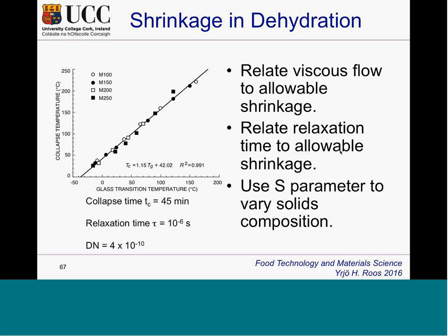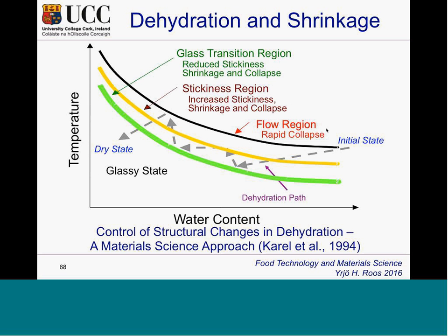There are applications in drying, and this type of approach is taken in pasta drying industries, where you like to keep close to the glass transition when the water is reduced towards this end, and then you can enhance the diffusion and keep the structure proper. But you also improve the quality in many other meals. And when you know the relaxation times above the glass transition, you have much better ways to do that. And if you apply that to spray drying or air drying, you can make formulations that are easier to handle.